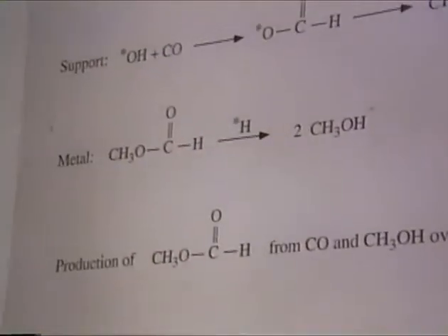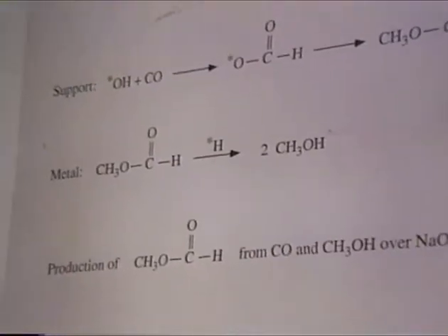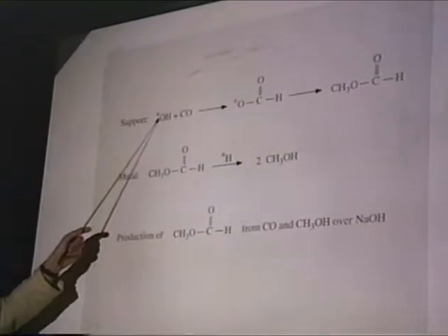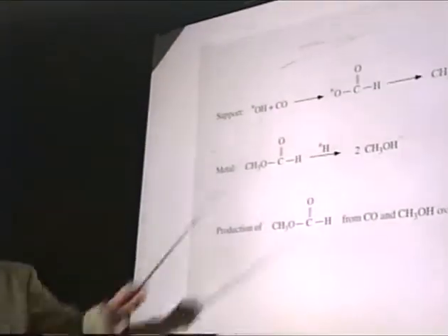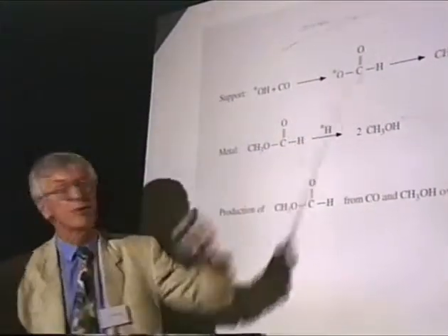A slightly different mechanism is through the gas phase. And that goes as follows. I recall that in the old days, methyl formate was made in the industry by sodium hydroxide. No metal needed. You took your sodium hydroxide, you had carbon monoxide, and the idea was that you're making a formate, and then with methanol you're making methyl formate. Now, what about hydrogenolysis? Suppose this is going through the gas phase to the metal, and then you get hydrogenolysis, and then you get two methanol molecules. And your only problem is how to make the first methanol molecule.